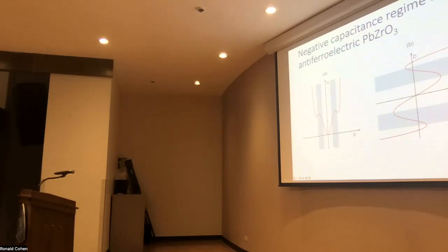We can turn this dependence into the equation of state. And from the equation of state, we can find two regions of negative slope, which is the same as negative susceptibility or negative capacitance regime. These areas are shaded, and we can see that this shading is actually associated with a maximum in the free energy. And this is the area that the system tries to avoid. The system doesn't want to live in that thermodynamically forbidden region.